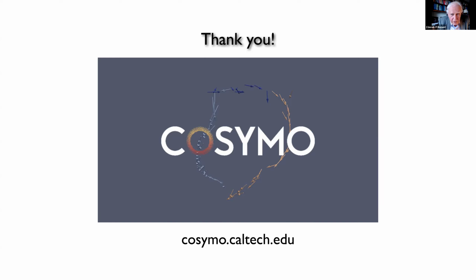Size effect introduced. Now, 1 in a million to do either by simulations or experimentally, you need to simulate the structure 100 million times to do Monte Carlo. So I think in the foreseeable future, you will need a mathematical model for the material RVE to progress to that scale. And this is the reality. We, for example, have shown that you can have two materials, one is 8% stronger in the mean, but at the level of failure probability 1 in a million, it is 25% weaker. And this is generally neglected.